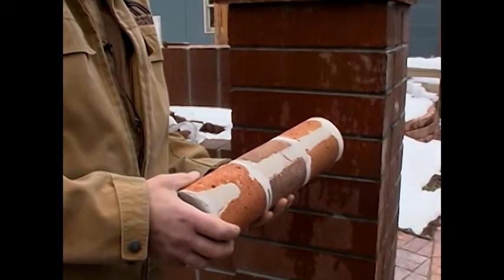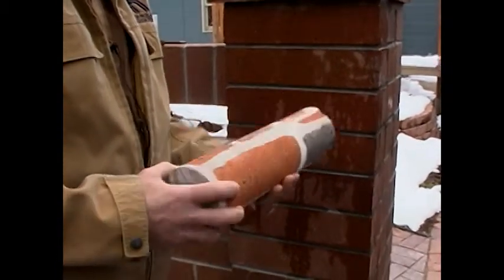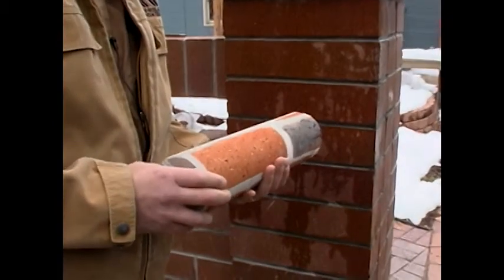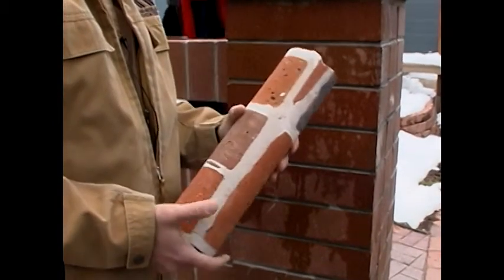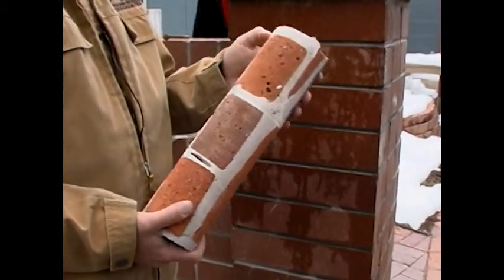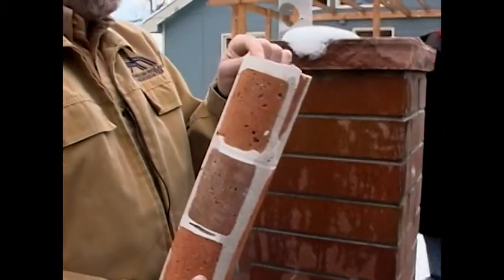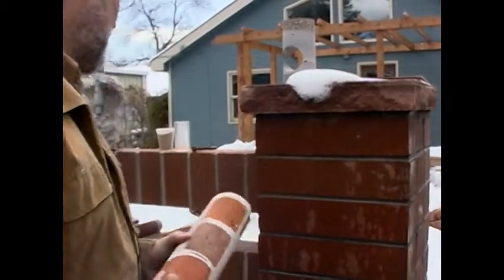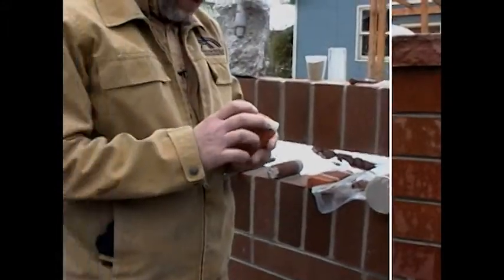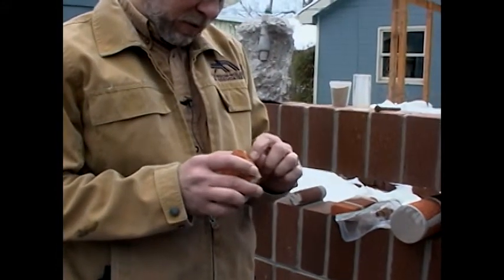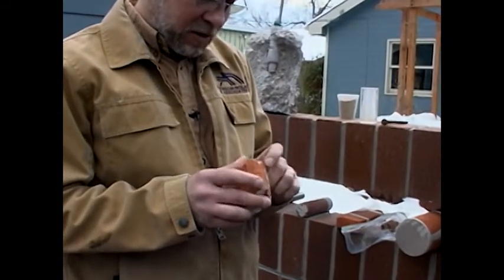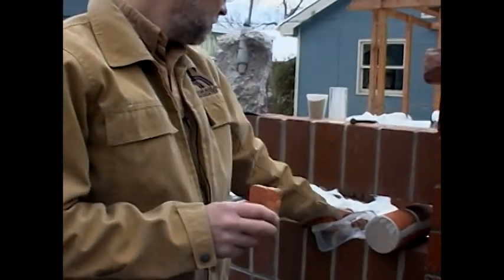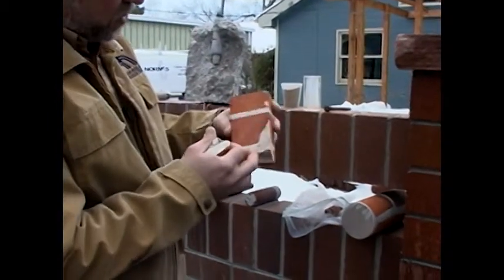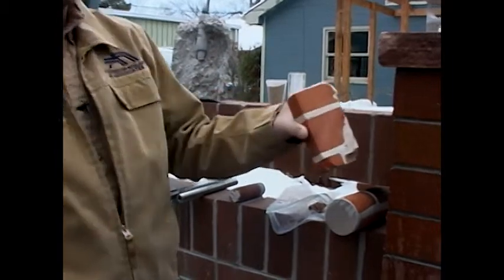But most of the time, we've got some really good mixes that just bond like mad, but yet they're kind of soft and squishy and have a good vapor transmission. We've been doing lots of vapor transmission tests. We've done very, very fine mixes for crack injection as well, ultra fine mix. That's maybe somewhat easier to see. Just cracks.